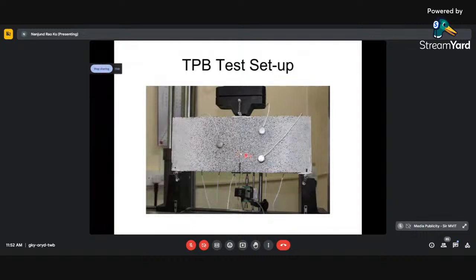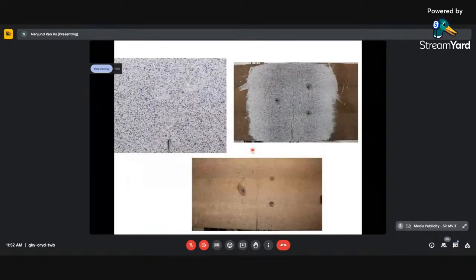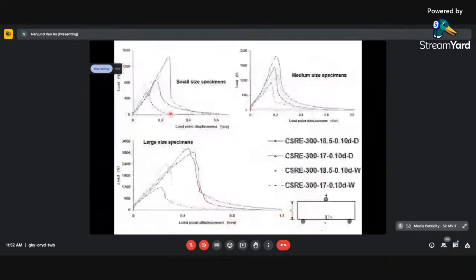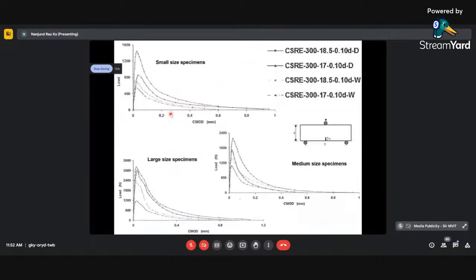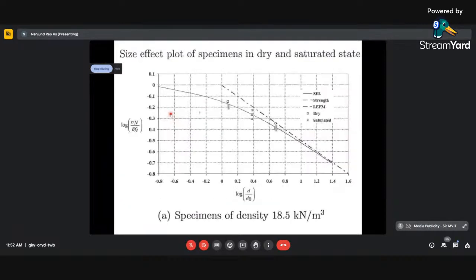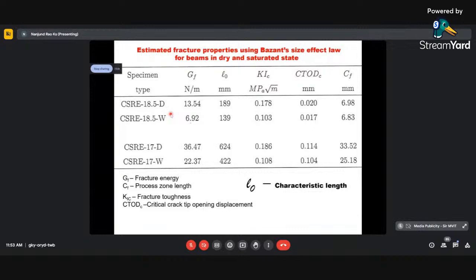Through the acoustic signals which they capture, we'll be able to know when the damage actually started inside and reached the surface. So this is how we do the test. You can see the failure has extended, the crack has extended, and this is the DIC pattern that we recognized. So the load versus load point displacement response for the fracture specimens for different things. This is load versus CMOD, crack mouth opening displacement, and based on all these results, we will be able to get the properties. I'll just show you here the fracture toughness, then the process zone, and other things.